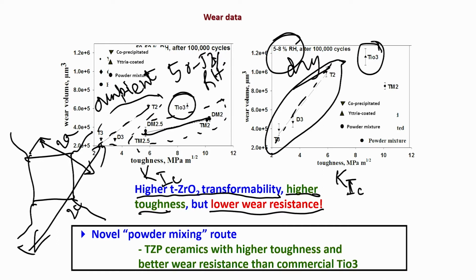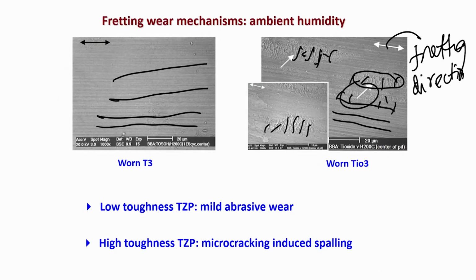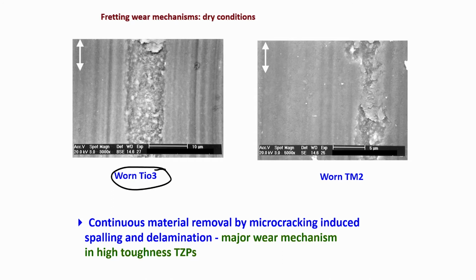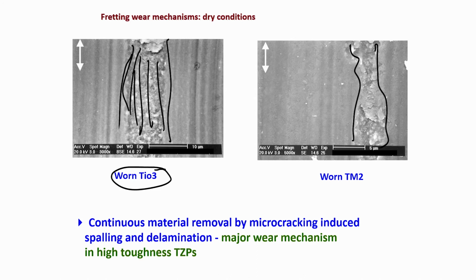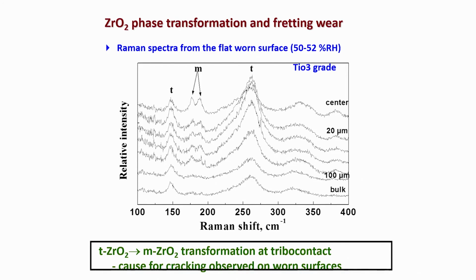This is one of the company's TiO3 ceramics, which is used to produce zirconia powder, and then we have simply taken the powder and hot pressed it at 1450 degrees Celsius. Now, in the trioxide ceramic also you can see very clear spalling, like a couple of groups of the abrasive groups are simply spalled off, and that is the case for this TM2, that is the TOSOH mixed powders, and there again that leads to spalling and delamination, in this particular case high toughness TZPs.